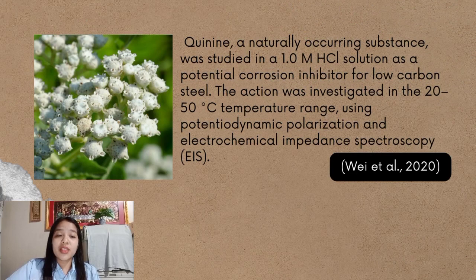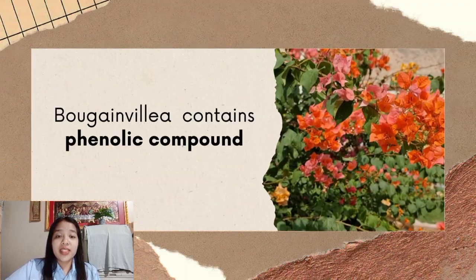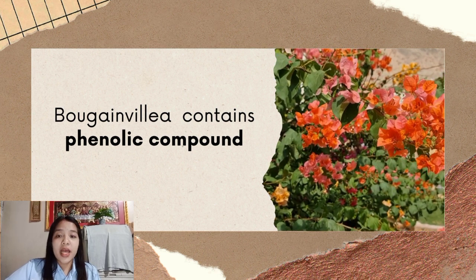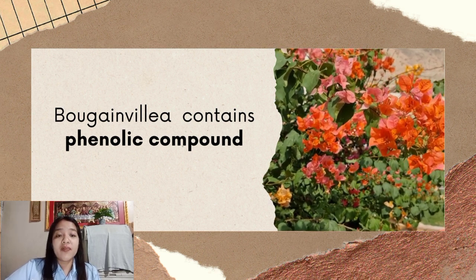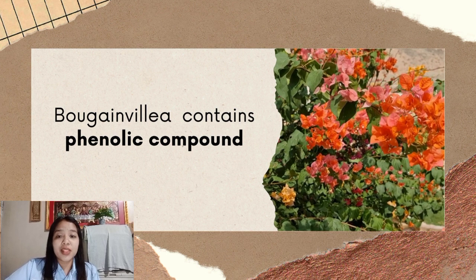Quinine, a naturally occurring substance, was studied in 1 molar hydrochloric acid solution as a potential corrosion inhibitor for low-carbon steel. The action was investigated in the 20 to 50 degrees Celsius temperature range using potentiodynamic polarization and EIS. Bougainvillea spectabilis leaves contain phenolic compounds, chemicals found in plants that have corrosion inhibitor effects.